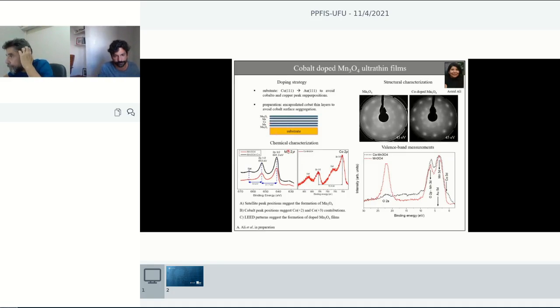So these are the manganese 2p core level peaks. Here's the cobalt 2p core level peak. And actually, you have here two peaks, the two envelopes correspond to the non-doped and the doped one. We almost don't see any change in the doped one.